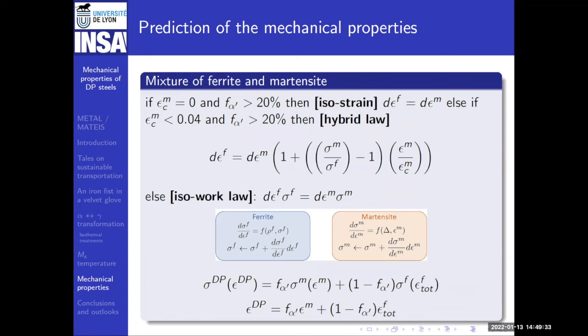But is the threshold the same for all metals, or do you also have different thresholds depending on the material? That I don't know. In fact, for our materials, martensite plus ferrite, we noticed that the threshold was 4%. Maybe for other materials, it can be different numbers. I'm not saying that it's a universal threshold. It depends on the properties of each phase.